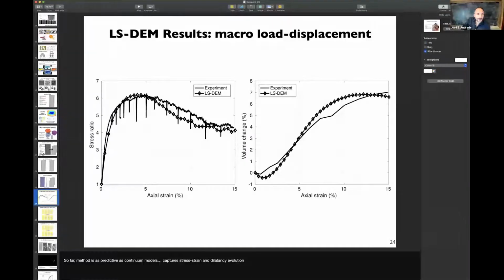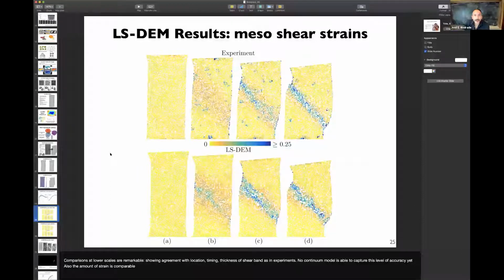And so you can see that the discrete element model, the level set, does exactly the same thing that a continuum model would do. So at this point, we are tied with the continuum model. With one caveat, we haven't calibrated a dozen parameters. All of our parameters are coming from the properties of the grains. We're not tuning anything. But we can push the boundary of the model even further and ask it to make predictions about physics that are happening at lower scales.